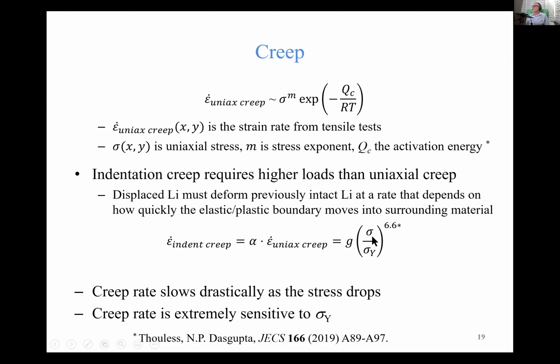local stress drops for whatever reason, the creep rate there is going to drastically slow down. It also means that the creep rate is extremely sensitive to what value you use for the yield strength. And this is going to turn out to be very helpful for us, because if you double the yield strength, then all the calculation goes bananas, and so it's going to severely limit the value of the yield strength that we can choose, given that we're using it as an adjustable parameter.